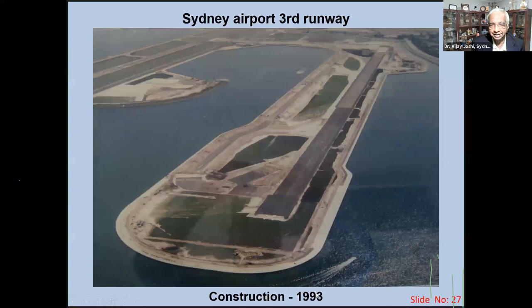Back in 1993, this is Sydney Airport. Third runway was built. There were two runways already there. So for the third runway, they put a tender there in '93 and the entire strip of the third runway was built by using slag. So this is the first critical one. And even today, if you see that in 1993, that was almost 30 years back, even today, any work around the airport, slag is being nominated. And it's not only nominated, it's being specified. That means they must use the slag because of the performance of the product.